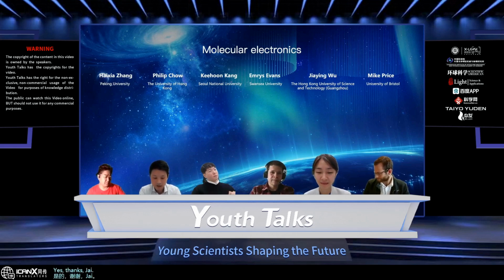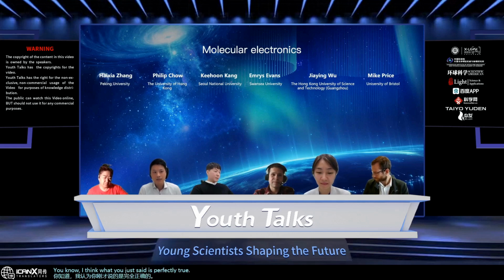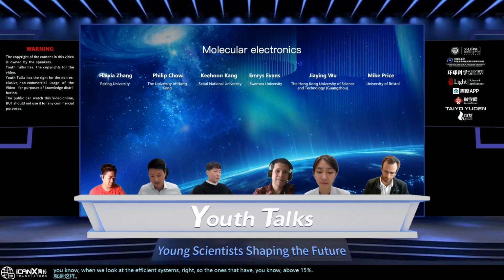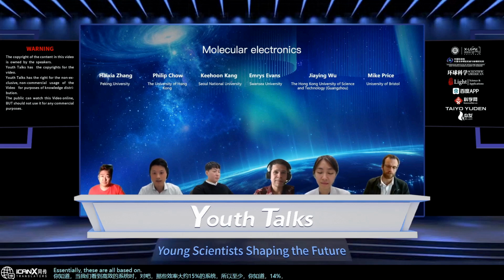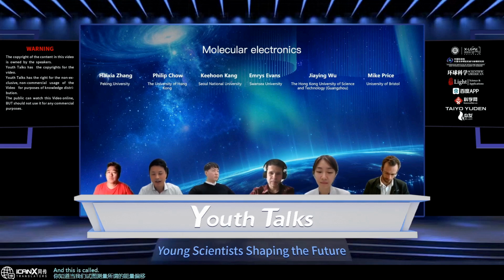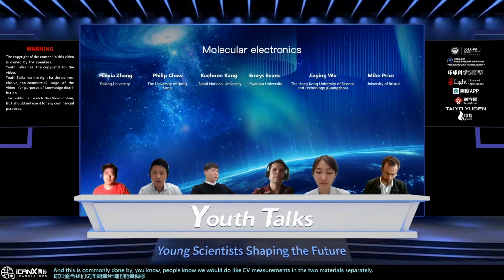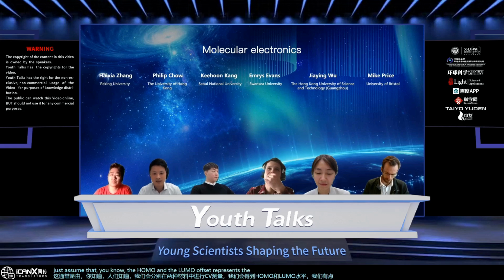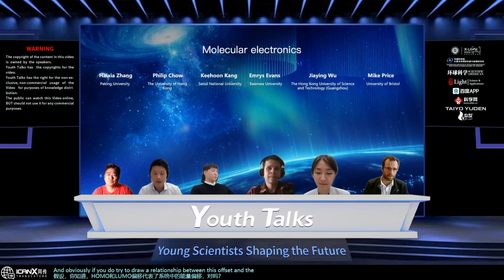Yes, thanks, Jiaying. I think what you just said is perfectly true. When we look at the efficient systems, the ones that have above 15% efficiency, so at least 14%, these are all based on the non-fullerene systems. And when we try to measure this so-called energy offset, commonly people do CV measurements on the two materials separately. We get the HOMO and LUMO levels, and we just assume that the HOMO and LUMO offset represents the energy offset in the systems. And obviously, if you try to draw a relationship between this offset and the device VOC, then most likely you would not get a very clear-cut trend.